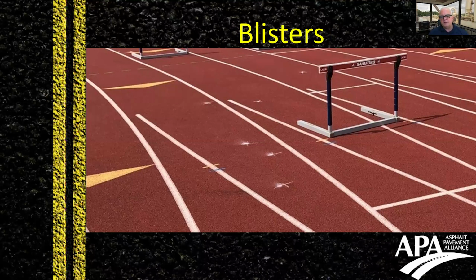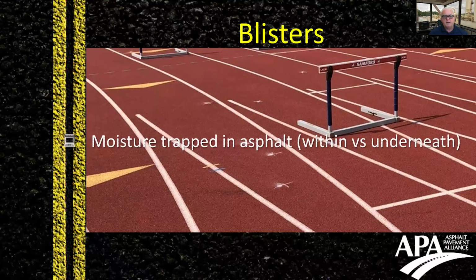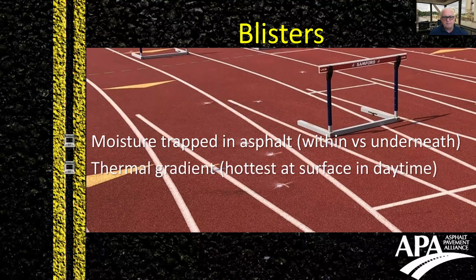Blisters is also something that you really want to avoid with these surfaces. You can build a really nice surface and be very proud of it. Perfect grade control and everything. And if you have something like this happen, that can really put a dark cloud over a project. And this happens when you have moisture trapped in the asphalt, either within it or underneath it.